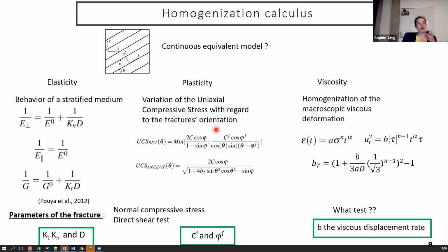Yes, so how does the REV behave? For its elastic part, the behavior is that of a stratified medium. Regarding the plastic anisotropy, the parameters are calibrated on the variation of the uniaxial compressive stress with regard to the fracture's orientation. And the parameters of viscous anisotropy are calibrated by a homogenization technique used to express the macroscopic viscous strain tensor.